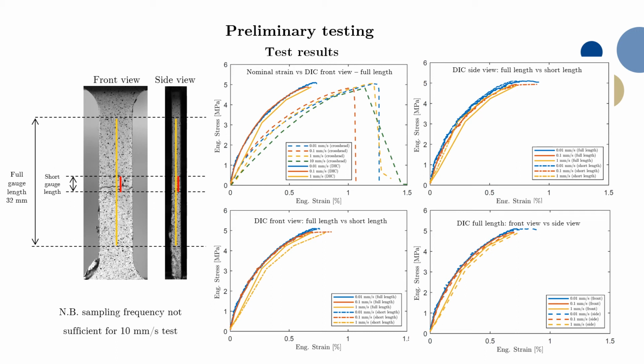The behavior is quite brittle, and in all the strain domain the curve is non-linear, and there is no evident shift between an elastic and a plastic region. For all the tests, the strength was well scattered around 5 megapascals, and the strain at break was always lower than 1%.